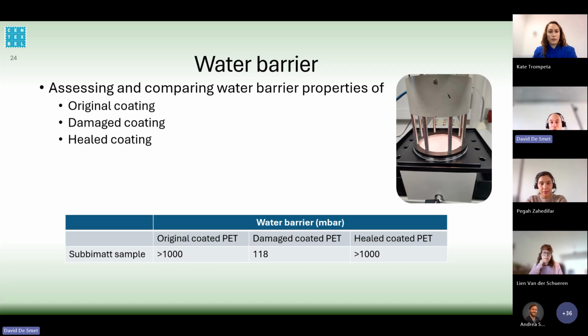Then we put a scratch under the coating, and then we see that the water barrier properties are dropping from 1000 down to 118. Once we do the healing test, we can see that we can recover the water barrier properties, since we have again resistance to hydrostatic pressure of 1000 millibar.